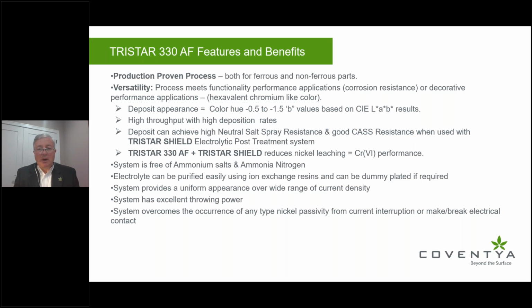Of course, we've always had in mind the design of ammonium-free types of technologies. Also, with trivalent chrome systems, they need to be purified a little bit differently than chrome 6. With chrome 6, we worried about just a porous pot to keep trivalent chemistry reoxidated to hexavalent chemistry. But here with trivalent, the electrolyte is purified with a resin system, and we can dummy plate if we have to. So we can do all the same things with trivalent technology that we've been successful with over decades with chrome 6, just avoiding the chrome 6 altogether.